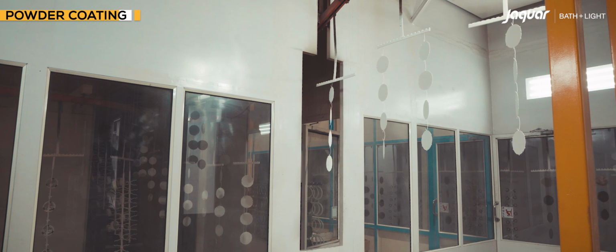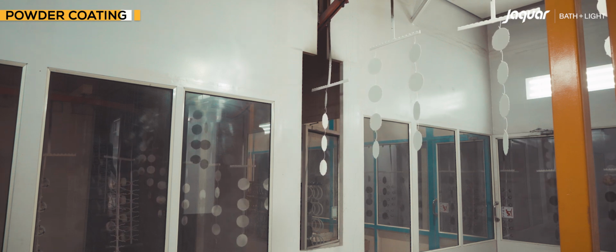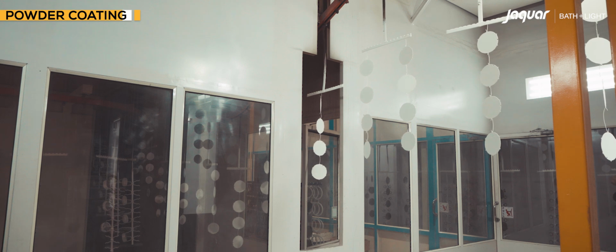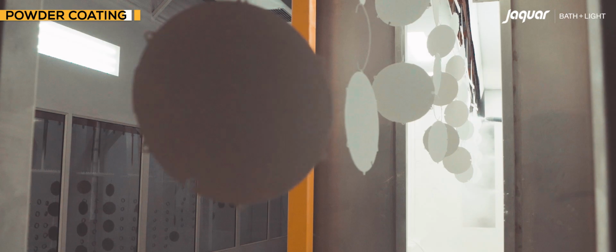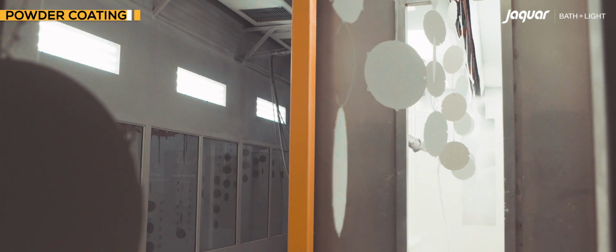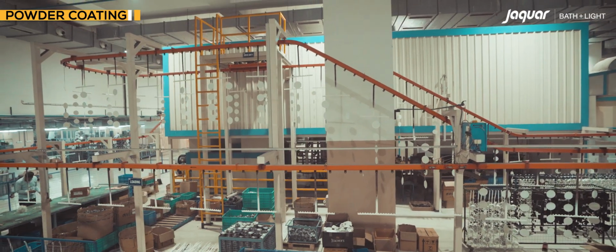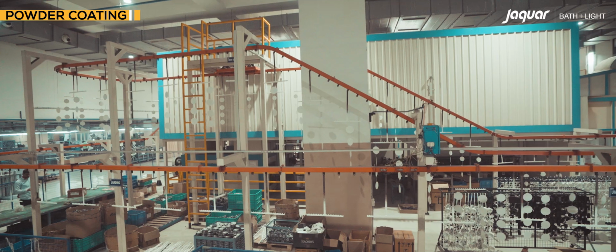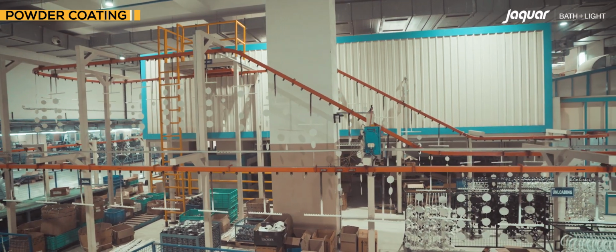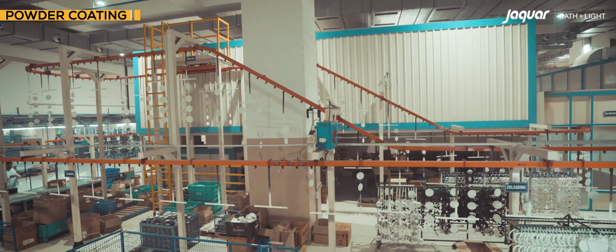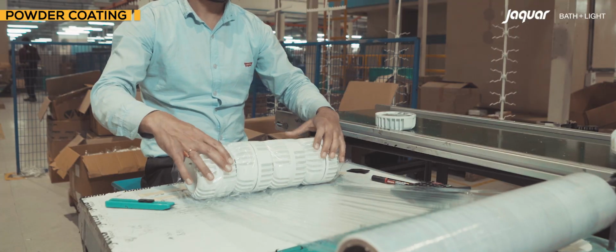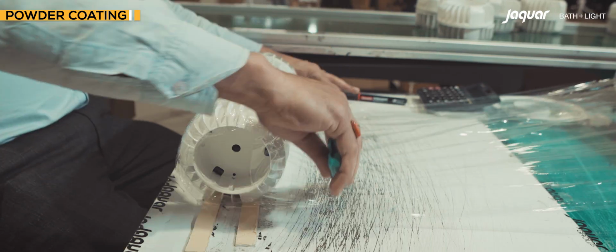After this process, the housings are baked in a furnace at 190 to 210 degrees Celsius temperature. A loop is created inside the furnace in such a way that each product gets baked for 15 minutes. Once it comes out of the furnace, it keeps moving in a loop in open air for 10 minutes to get cooled. It is then taken out and dispatched to the assembly section.